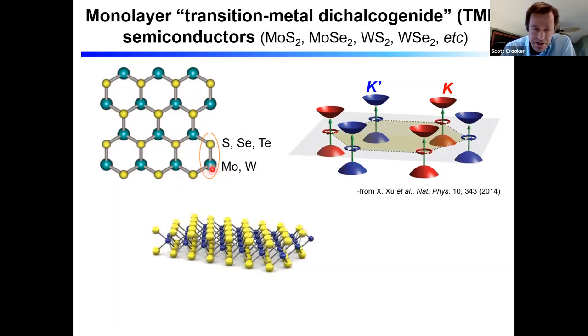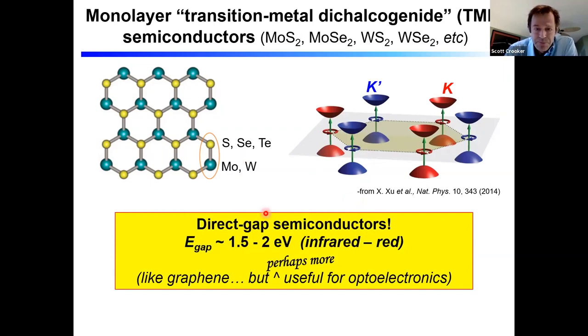But because they have different atoms in the unit cell, whereas in graphene we'd have nice Dirac cones at the corners of its hexagonal Brillouin zone, in these materials we do not have Dirac cones, but rather there opens up a fairly significant semiconductor band gap. And the key point here is that in their monolayer form, this is a direct semiconductor band gap, and it's pretty big. It's 1.5 to 2 electron volts. So in wavelength, that's between infrared and red. So immediately pretty interesting for all sorts of optoelectronic applications. And I have to be a little careful to whom and how I say this. I don't want to offend my friends who work with graphene, but I think it's okay to say that these materials have some similarities with graphene, but perhaps they're more immediately obviously useful for many applications in optoelectronics, like light harvesting or light emission technologies.